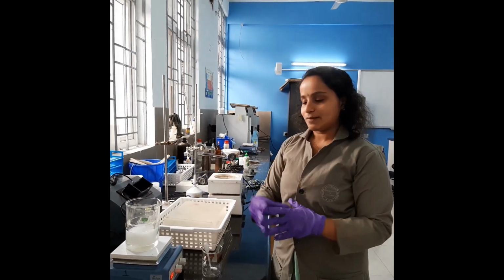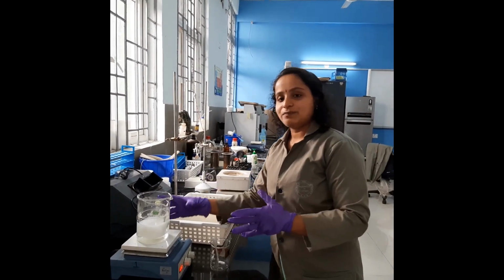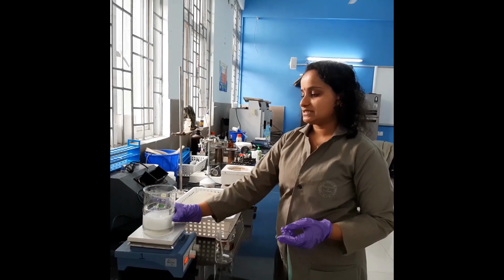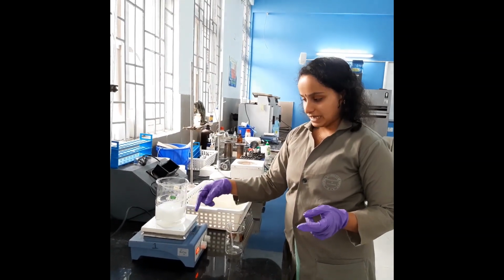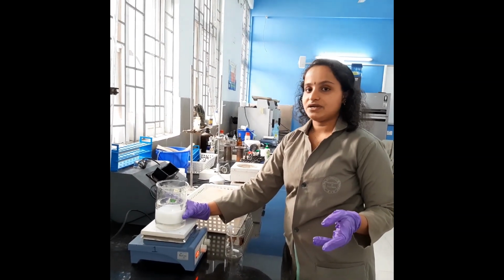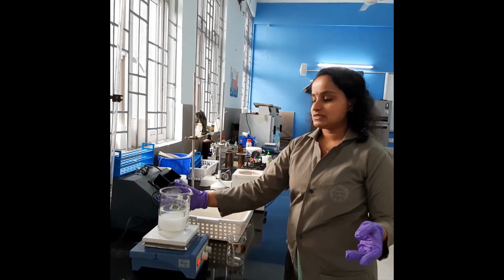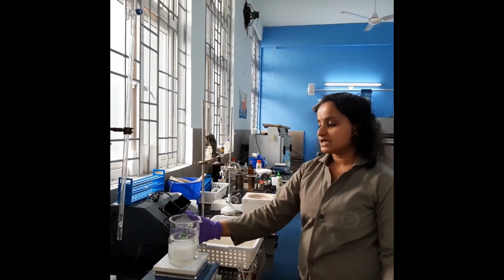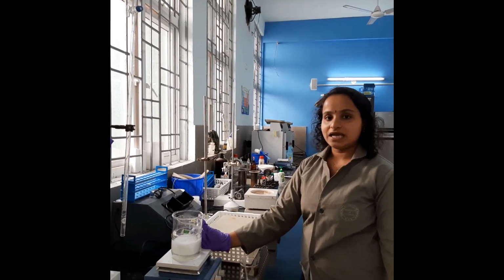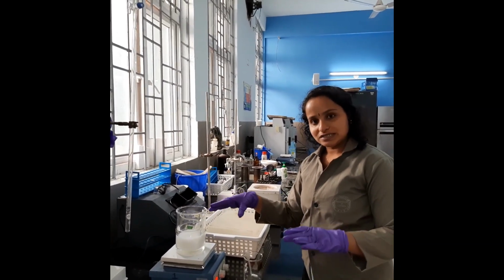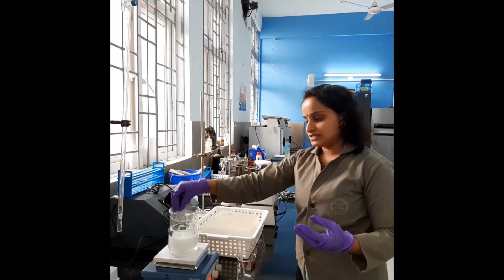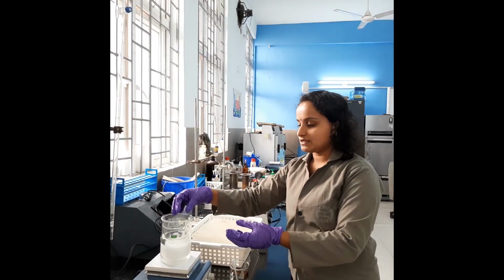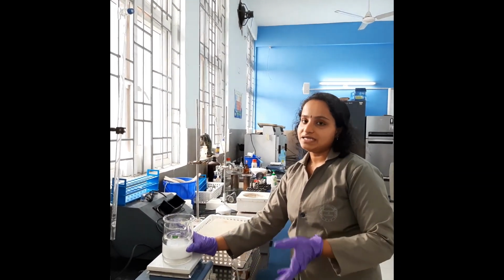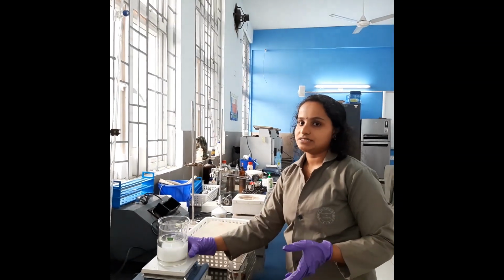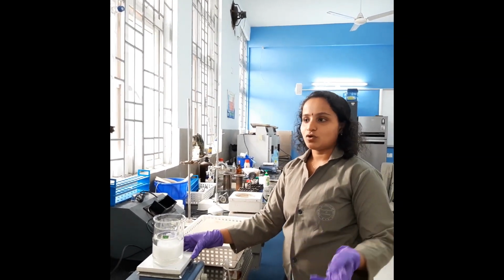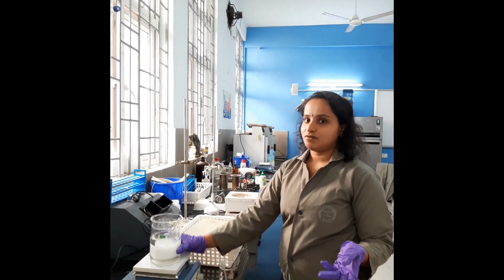So in order to precipitate all the metal ions completely and in order to maintain the pH uniformly, we have to stir the solution for 2 hours in this water bath condition at 65 degrees Celsius. So we will allow to stir this for the next 2 hours. After that we will allow for aging. Aging means allow to settle, means allow to grow. Without stirring, we will switch off the stirring and we will allow for aging for 18 hours in this 65 degrees Celsius water bath condition. Then tomorrow by this time our magnesium hydroxide will be ready.